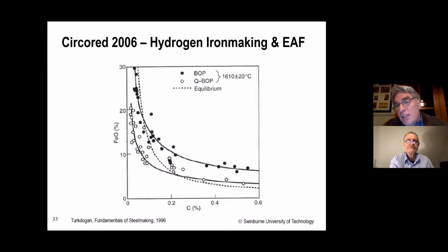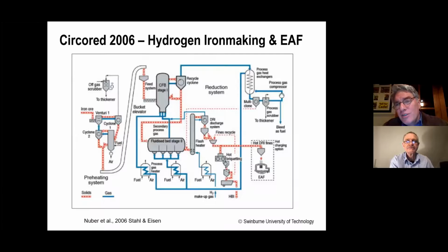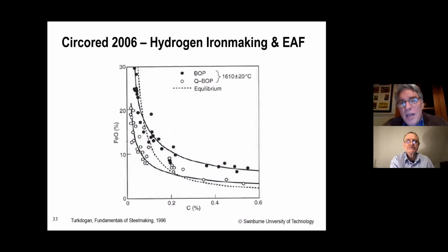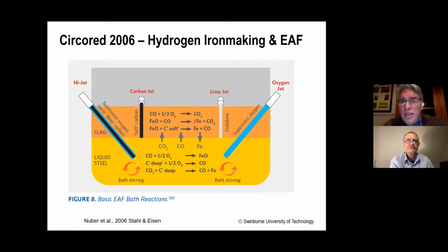One thing to appreciate is that the iron made from this has almost no carbon in it. So it's basically carbonless, an iron, not a steel, a kind of iron with no carbon in it. And when you have irons of low carbon, and you put it into the next process, what tends to happen is you make a lot of FeO. This is to do with the chemistry of the system. You make a lot of FeO in the slag. And that's exactly what happened when they put it into the furnaces. And these people, to get over that problem in the electric furnace, had to inject carbon to reduce the FeO.